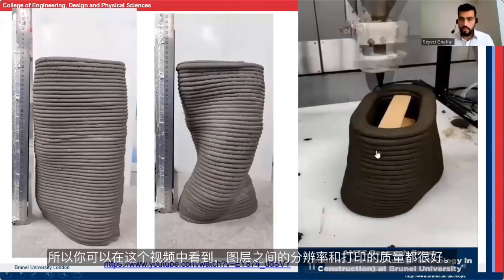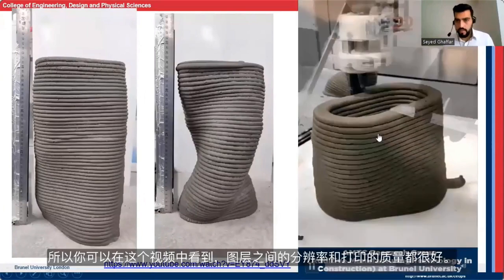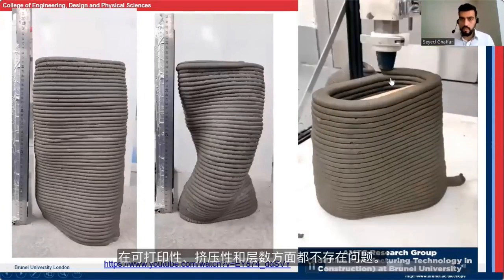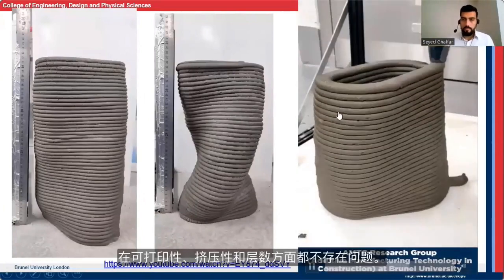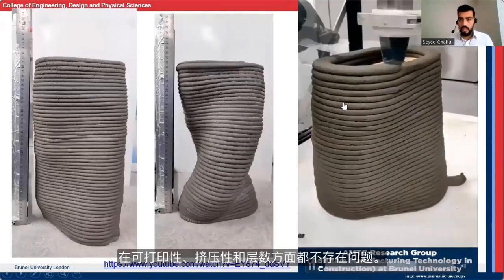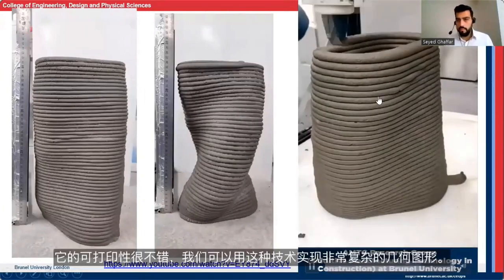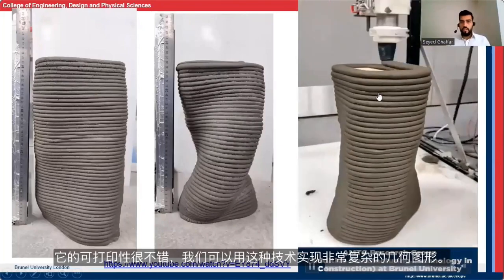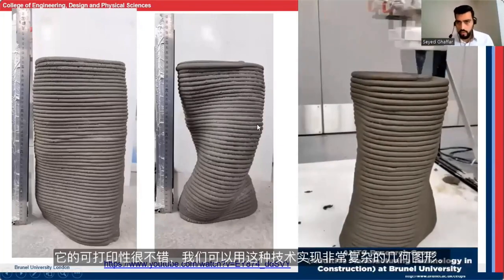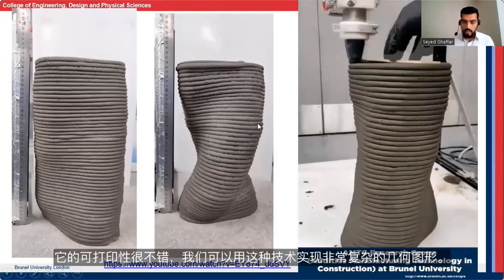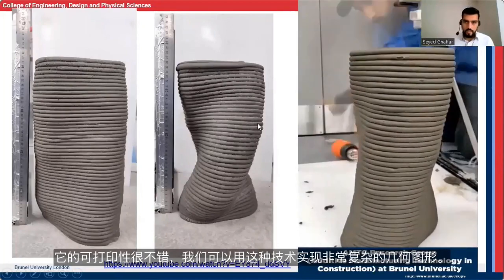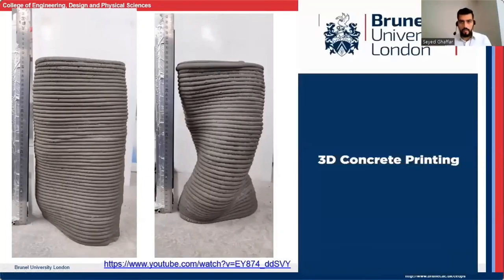So you can see in this video, the resolution between the layers, the quality of the print, is very good. There is no issue with the printability, the extrusion, and the layer height. The buildability is actually quite good. And we can achieve very complex geometries using this technique, with this material, geopolymers.